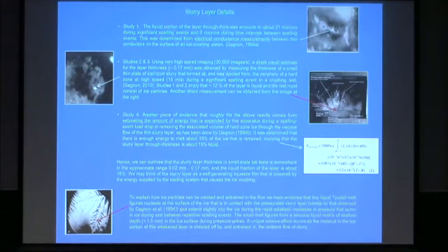So to explain how pieces of ice can break away from the hard zone surface, Tyndall figures, or these melt figures, they were named after John Tyndall, form, and they go to a very shallow depth, like a fraction of a millimeter within the hard zone surface, and that matrix of tenuous melt figures in there, they're very thin, like 20 microns in thickness, and they can soften the top surface, like a sub-millimeter thick top surface.